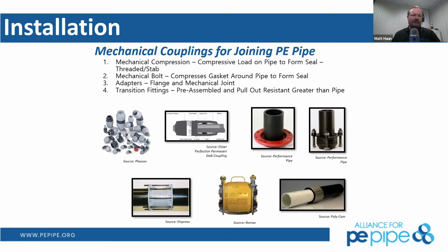So looking at this group of, what is it? They're Plasson fittings. Essentially, you're doing a compression nut over the fitting itself that activates that sealing force. For this Elster Perfection fitting, it's a stab fitting, so it's kind of finger trap like, whereas you apply the tubing end into the fitting, it gets trapped, and it also energizes some O-rings within there. For mechanical bolt type fittings, you've got to tighten these bolts, which the compression between these two plates actually is on an angle with an elastomer that squeezes the pipe surface itself. Or additionally, for this Romac type fitting, you tighten a couple bolts and it basically squeezes a seal to squeeze the outside of the pipe.